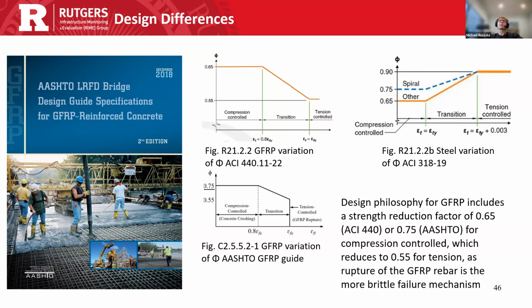So rupture is penalized in the code, all the way down to 0.55. So there's that very large reduction. There's very little strength loss over time with this rebar, and that's already corrected for with an alkali degradation environmental coefficient. So, since this product has a brittle failure, it's penalized multiple times to ensure that failure is statistically accounted for.